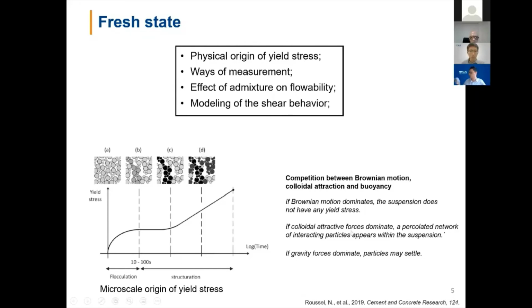If the colloidal attraction forces dominate, that means the cement particles would like to be touching each other. And then they will form a percolated network with interacting forces. And the whole matrix will have some type of strength. And this is what we want when we want the cement paste to harden faster, to set faster. If the gravity force dominates, then the cement particle will simply sink down. And this will result in a significant segregation and bleeding problem. And this is something we want to avoid.